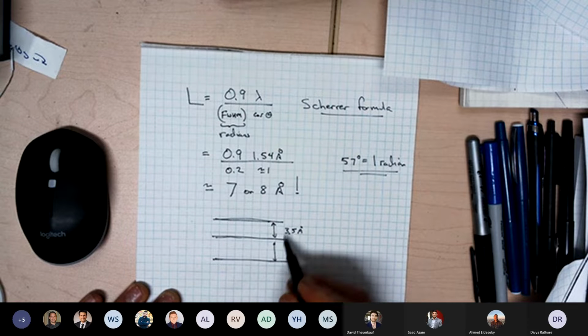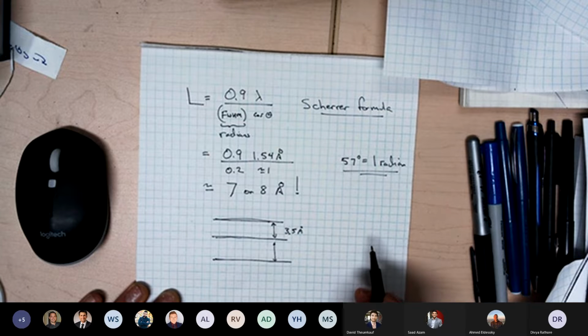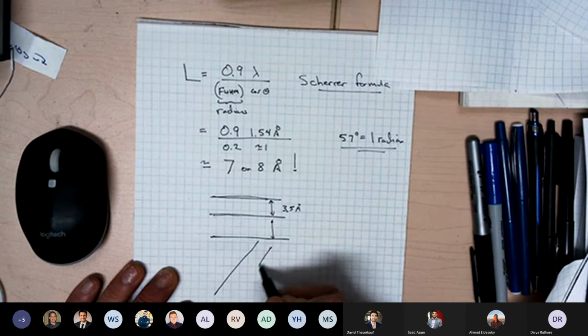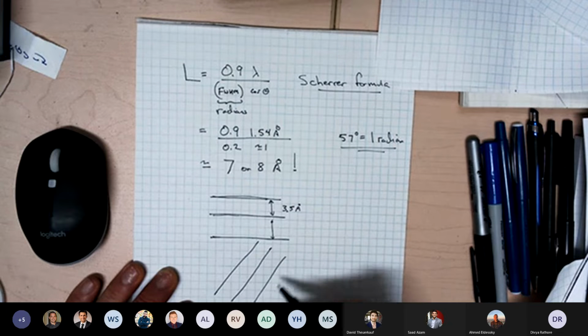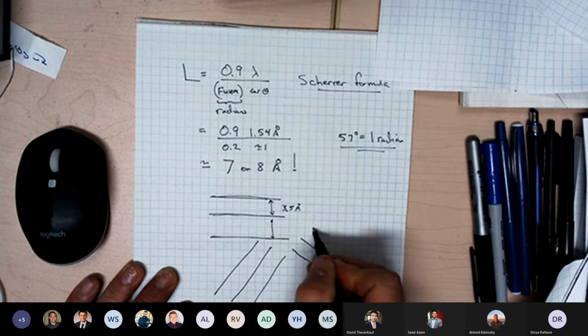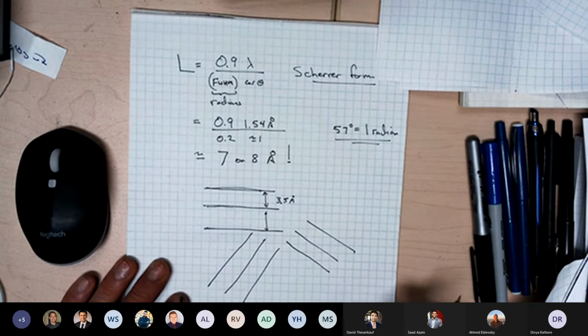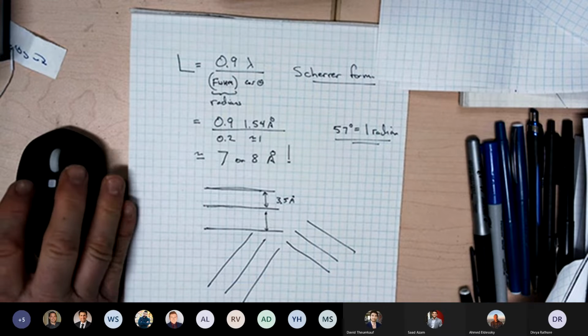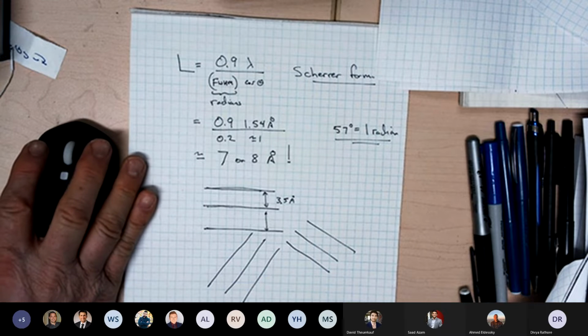Just one, or there's 2 or 3 stacked in a parallel fashion. Okay, and then they go off at some other angle in some other way, you know, like this. So when the peak is really broad, it tells you there's not very many of them stacked in a parallel fashion. So X-ray diffraction is really useful for looking at this. I'll go back to the PowerPoint.